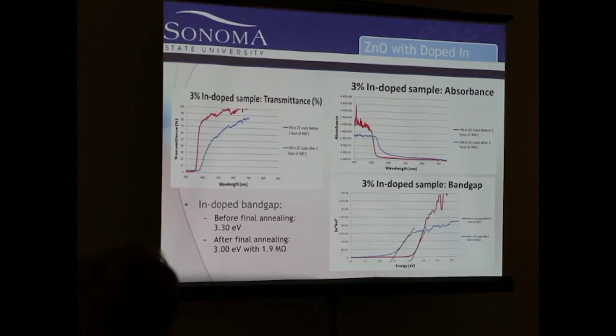So then separately, I doped my samples with indium, and that was really just to get a conductive thin film. So this one was a little bit of a different process. We stuck to one concentration, which was 3%, which we read from other articles said 3% is good for conducting. So here we have this red line.